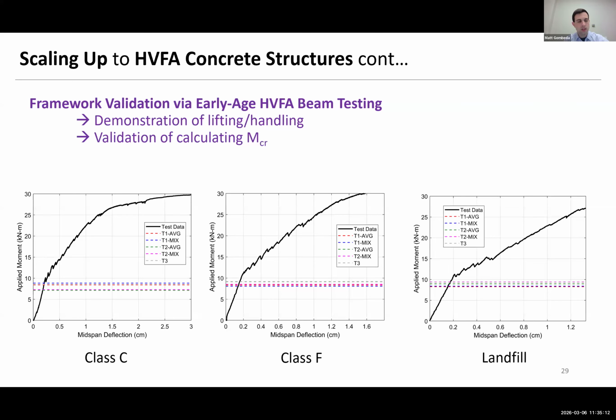So when you use maturity versus when you use just the concrete strength versus time, and when you do actual modulus of rupture testing, you're going to get slightly different estimates of how you can calculate the cracking moment of the beam, which is something that we focused on because, again, with early age lifting and handling, it's a primary design objective in precast. So our comparisons are pretty close. They're a little conservative, but they're within a reasonable amount of error, and we felt confident in our framework and the underlying method used to predict the cracking moment strength.